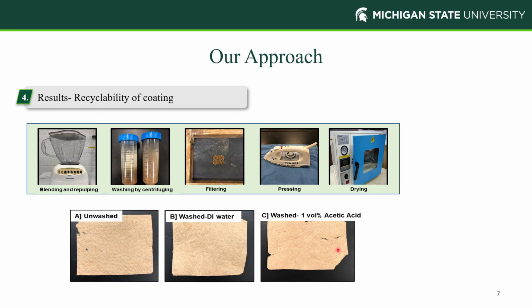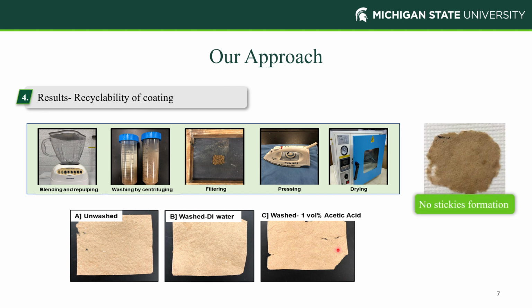and our FTIR results have successfully proven that the coating is not present on the coated papers after the washing procedure. And another advantage of our recycling process is that we form no stickies, as opposed to the existing approaches, and there is no hampering to the recycling process.